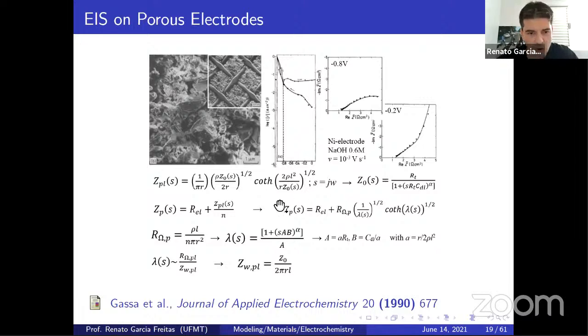The ZP is the overall impedance, it's the most important equation, because according to Gassa, the overall impedance of the pore is the electrolyte resistance, and this one, the impedance of a cylindrical pore. And we can observe several equations here, but the main result obtained down here was this one. The total impedance, the overall impedance, is the electronic impedance plus the impedance of the cylindrical pores divided by N, where N is the number of pores we have.